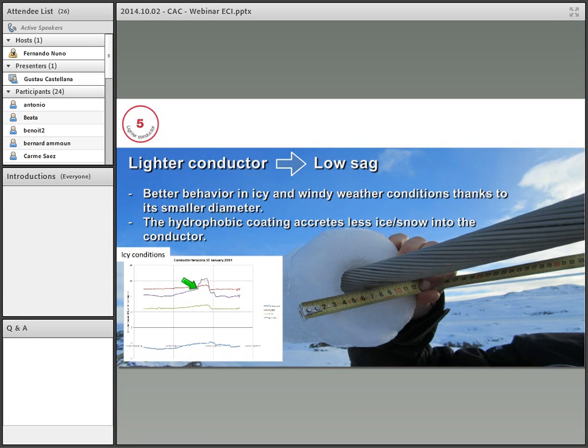At some point it starts to have more snow, which is what we call wet snow, because it was snowing around 0 degrees, and the conductor got heavier. So you can see how the ice made the load on the tower higher than on the control conductor. And even though there was a little bit of accretion on the copper conductor, it goes down really fast, while on the control conductor it goes down, but it takes more time to remove the ice created on the conductor.